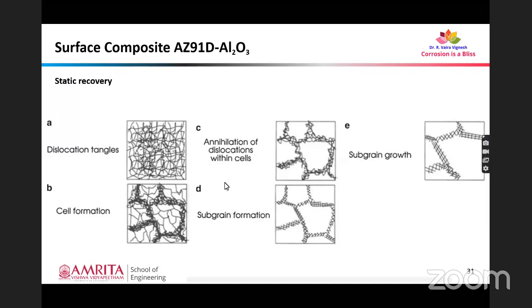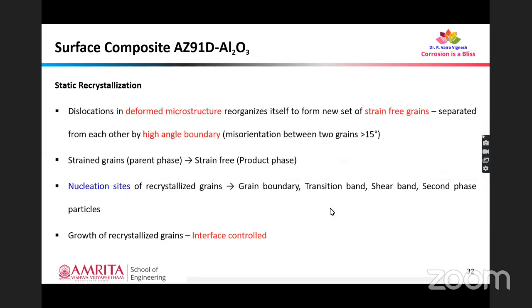So this does not happen in FSP, but it happens in some other processes if it is subject to some external heat treatment after friction stir processing. Okay, fine. So if the dislocations in the deformed microstructure reorganize themselves to form a new set of strain-free grains, then it is called static recrystallization. We could identify the static recrystallization phenomenon that has happened to the material through high angle boundaries. And added to that, if recrystallization happens, there will be strain-free grains from the strained grains. That is, the parent phase, which are strained grains, will develop into strain-free grains, which is the product phase.